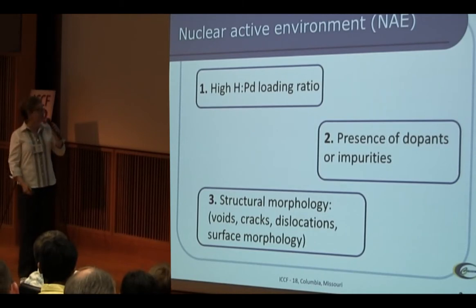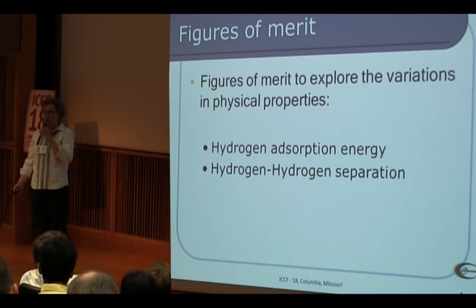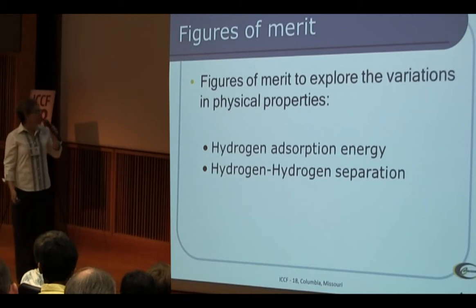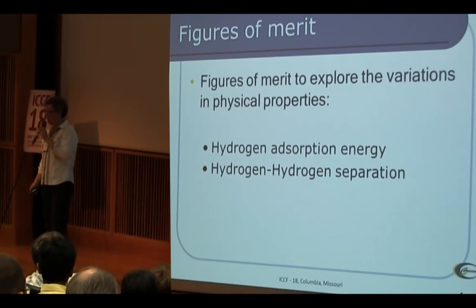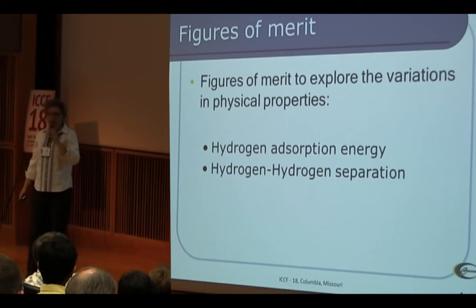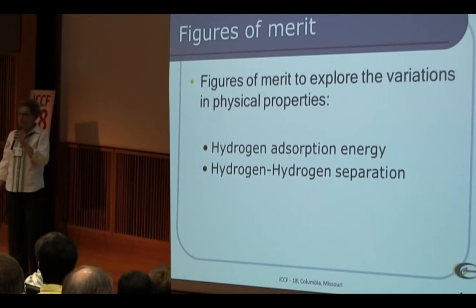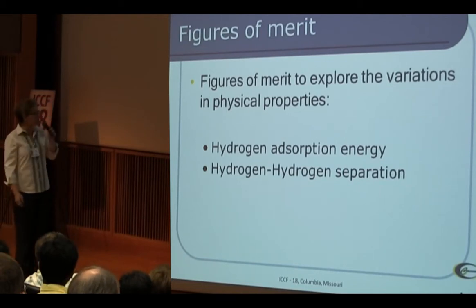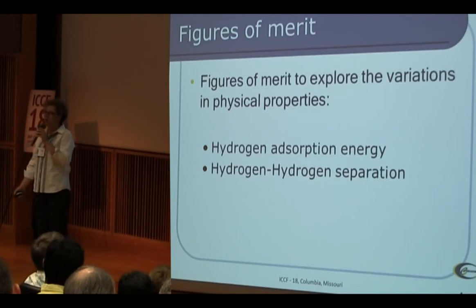I'll show you the results of those simulations and how we evaluate whether a material is good or a configuration is not that effective. We had to come up with figures of merit. One of them we decided to use is hydrogen adsorption energy. Most of the simulations you will see were done with surfaces, so hydrogen adsorption energy of the surface can be a good measurement tool. Another figure of merit we borrowed from Peter Hagelstein. He presented a very interesting talk about monovacancies in bulk palladium, looking at the separation of two hydrogen atoms and how close they can get within a lattice. Obviously, the closer they come, the higher the probability of the reaction.